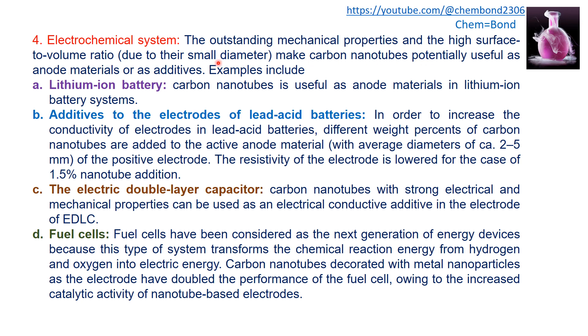Examples of electrochemical applications include lithium-ion batteries, where carbon nanotubes are useful as anode material, and as additives to the electrodes of lead-acid batteries to increase electrode conductivity. Different weight percentages of carbon nanotubes are added to the active anode material. The resistivity of the electrode is lowered for the case of 1.5 percent addition of nanotube material.